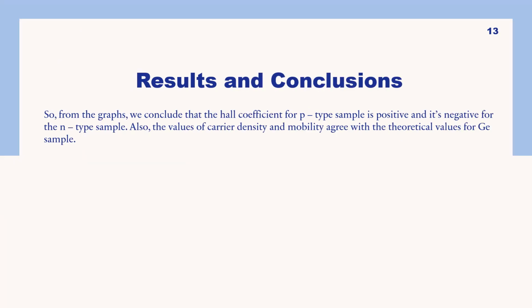So from our experiment, we found out that the value of Hall coefficient is positive for p-type semiconductor samples and it's negative for n-type semiconductor samples. And we found out the charge carrier density and carrier mobility for both the type of samples, and those values agree with the theoretical values. And we also noted that the values of Hall coefficients do not change for the range 0 to 10 milliampere Hall current for both the samples.